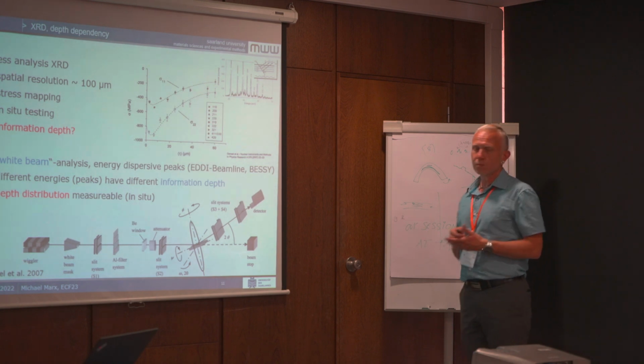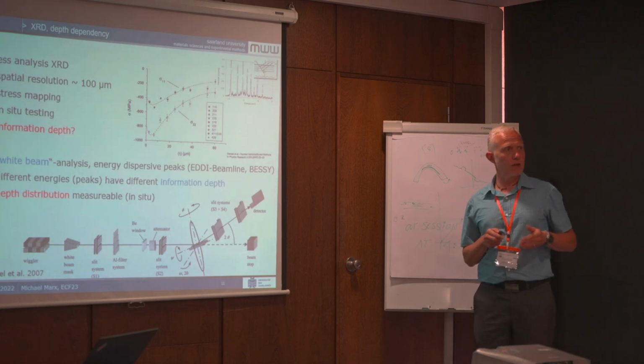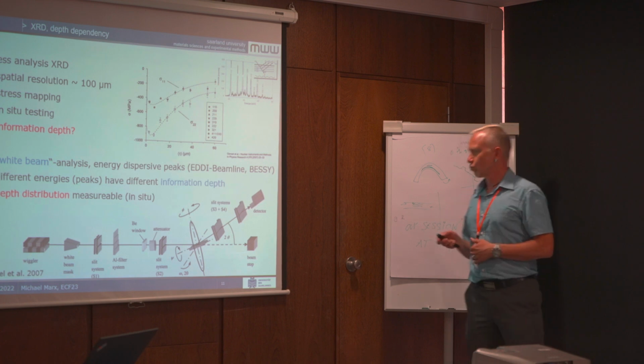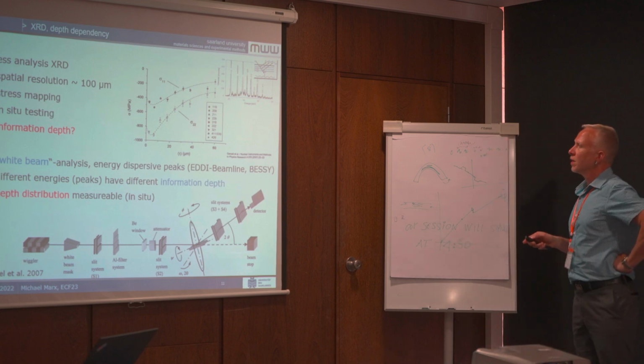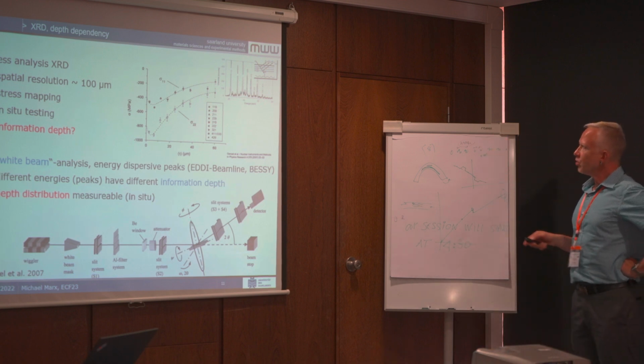We can do this by in situ testing. So we have a pre-fatigued specimen, and then we load it in the synchrotron, and then we can measure the stress distribution in front of this crack. And now what about the information depth?